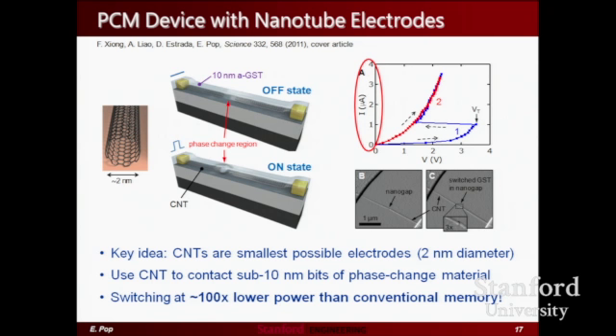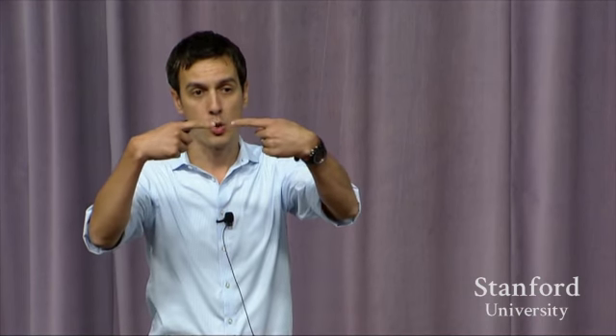So we took carbon nanotubes. Carbon nanotubes, I mentioned earlier, are these one-dimensional, wonderful electrical conductors. And their diameters are on the order of 1 or 2 nanometers. So it's absolutely impossible, to my knowledge, to make an electrical conductor that is less than that and functions reliably at room temperature, right? So we took individual carbon nanotubes and used those as the contacts, as the electrodes, to probe phase change memory materials.